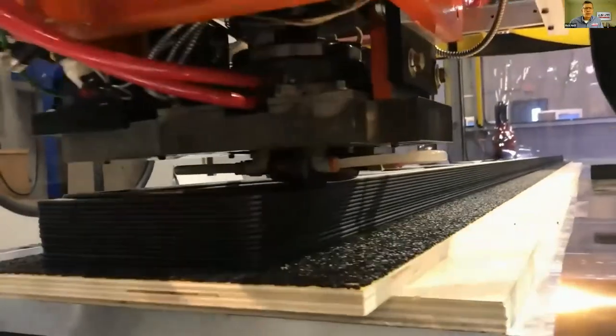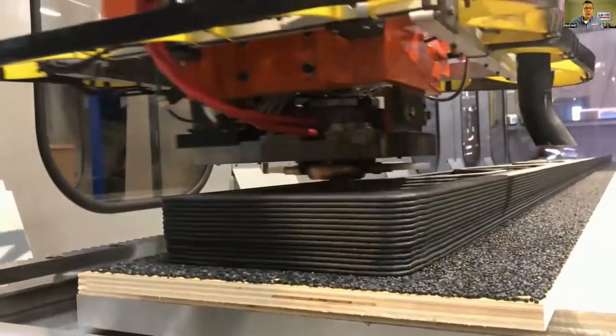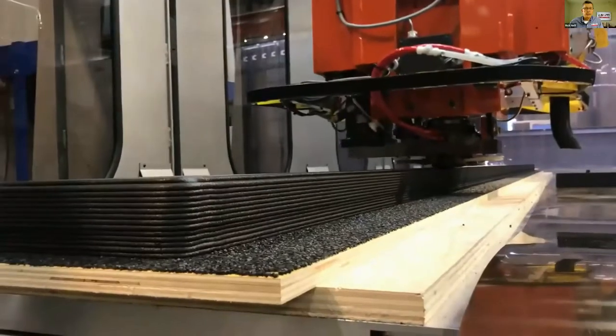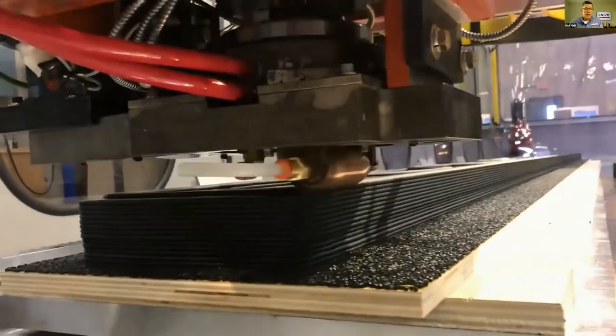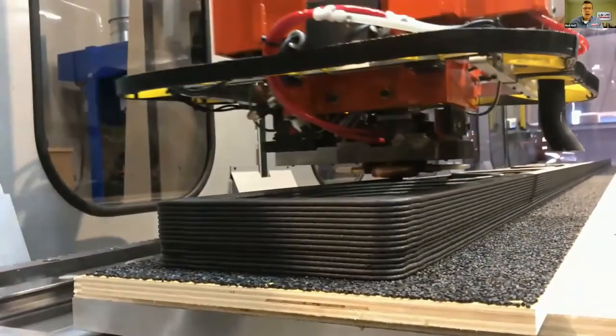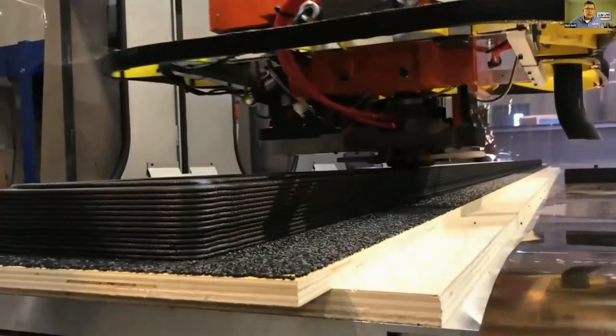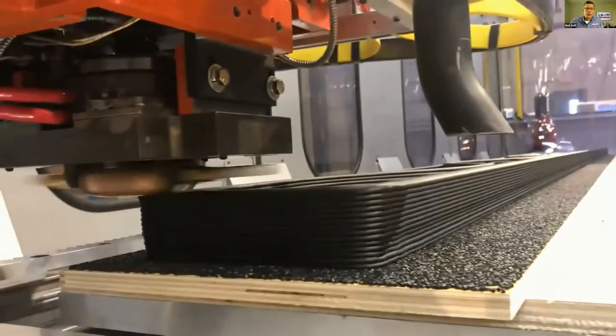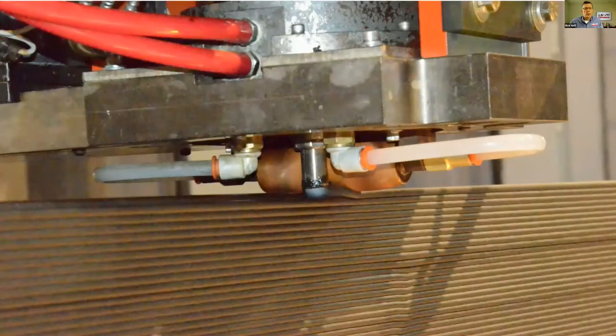So at Oak Ridge, they discovered this property that they call the Goldilocks effect. If the part's too hot, you find that when you print on top of it, the material can't support the weight of the material on top, and it kind of slumps down or droops. If it's too cold, the materials don't bond well together. A little further investigation into that, and THERMWOOD has developed what they call the continuous cooling process. So what happens is that when you put a layer down, when you use a really large layer like THERMWOOD does, when it starts to cool, it cools along the outside edge and along the top to where it cools enough that it could support a new layer on top. When the new layer comes along and is deposited, it's hot enough that when it's forced into the layer below it, the material melts through to the molten core of the lower layer, and the two layers are bonded together very effectively.